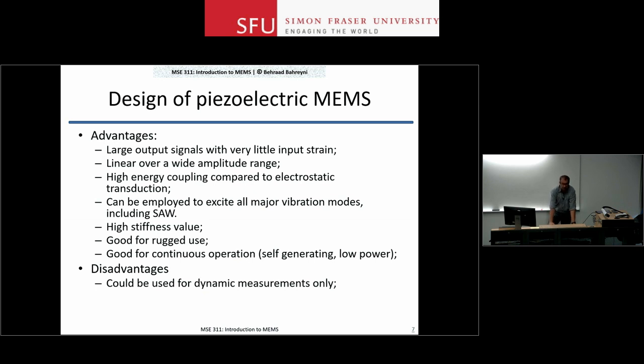But there are disadvantages. And the major one for piezoelectric transduction is that you have to have an AC signal. It has to be vibrations. You cannot really look at them to measure a constant force. The reason for that is that you apply a constant force to this electrode, you produce charges on the two electrodes of this capacitor. That's all good, but the problem in real life is that there's always leakage mechanisms. So you produce that charge, and we saw that it doesn't have to be a large amount of charge, like 40 picocoulombs of charge. And if you have any sort of charge leakage mechanism here, that charge will disappear fairly quickly. So piezoelectric transduction in general is not good for DC sensing.